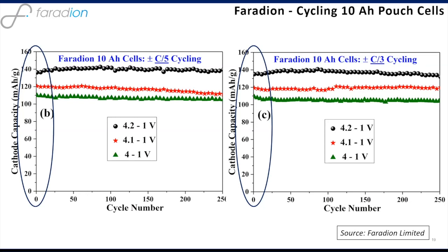And we're running them at different depths of discharge. 4.2 to 1 volt is basically 100% depth of discharge. I'll just draw your attention to two things here. One, this cycles with very low capacity fade at 100% depth of discharge. And two, the cathode at these relatively good rates of charge and discharge is still delivering 140 milliamp hours per gram specific capacity reversibly. That's a really good result.